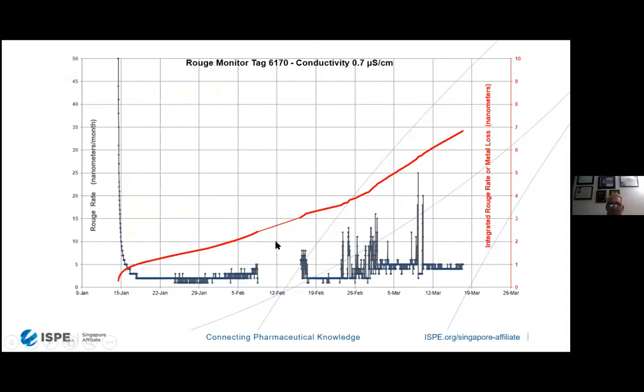In order to look at this on a longer data period, same installation date. The red line, once again, is accumulation over time. So now we're looking at 2 months, and you can see the rouge accumulation is almost 7 nanometers over that 2-month time period. But down over here on the blue line, you start to see peaks going up and going down and then going up higher and coming down. And the question is, well, what is this data and what does it actually represent? You can see nanometers going up to as high as 15, 16, even 20 to 25, and then coming back down again. So we're going to concentrate on the data right over here, and I'll explain what's going on.